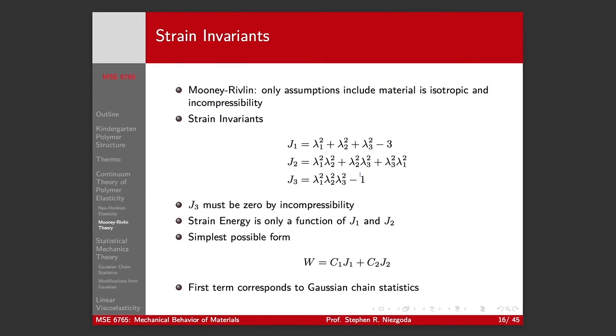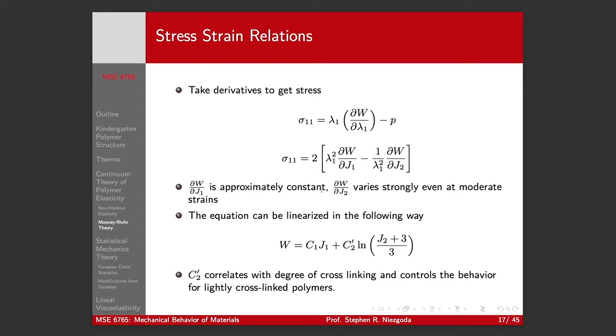And the theory is written in terms of invariants of the strain tensor. We'll call them J1, J2, and J3. Just like we had the invariants of the stress tensor, the trace, the determinant, and the I2 term, we can compute the same invariants for the strain tensor, and we'll label them J. This is basically the trace of the strain written in terms of the stretch ratios. Now, from our incompressibility condition, J3 has to be zero. So, we know that our strain energy can only be a function of J1 and J2. Let's pick the simplest possible form, which is just C1, J1, plus C2, J2. The first term, again, is going to correspond to our Gaussian chain statistics. This is a deviation from linearity. So, here's our strain energy. Let's take our derivatives to get the stress.